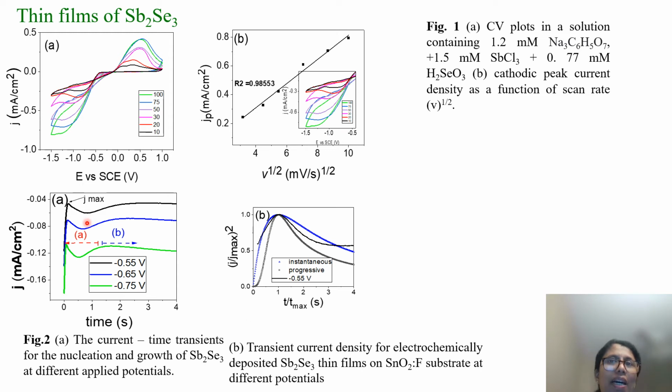The curve can be divided into regions, this region as A and this region as B. An increase in the current density is associated with the nucleation process, followed by a diffusion controlled process. Here there is an increase followed by diffusion control, but then a saturation growth, a region where the current density is constant, indicating saturation growth.